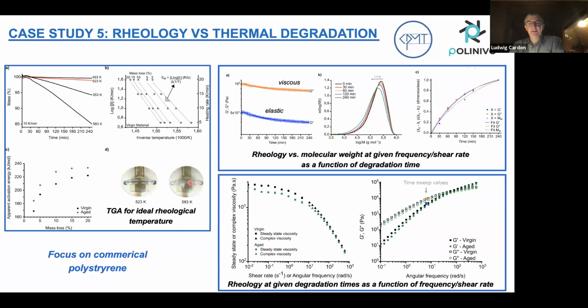So we use plate-plate rheometry. We use TGA also to define the ideal rheological temperature we want to apply. And then we look inside the rheology versus molecular weight and the rheology versus a given degradation time. Why is this finally important?